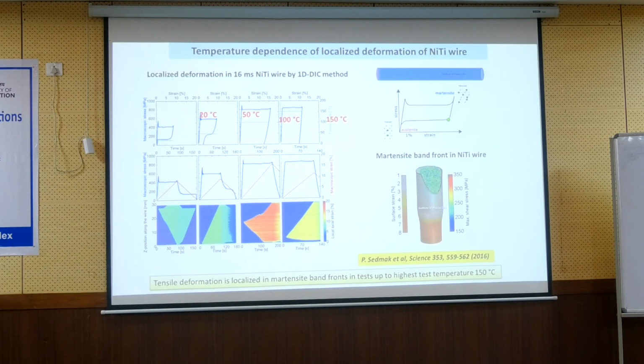So we observe this plateau. So if you take the wire and you measure it in tension, you will see that the stress remains constant. And this is because the deformation occurs in such kind of localized manner. So this is a sort of shear band which propagates during the wire upon loading and unloading. And this is a big complication because normally the material deforms in homogeneous matter, but nitinol deforms in this localized manner. And you have to somehow take this into consideration, and